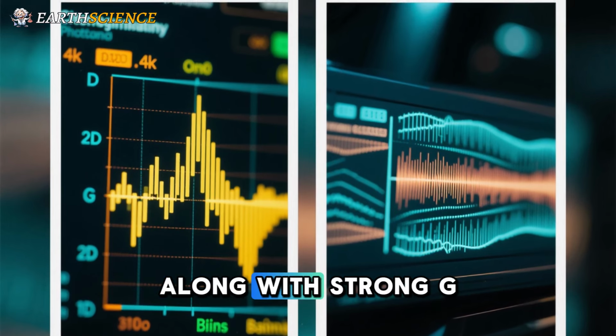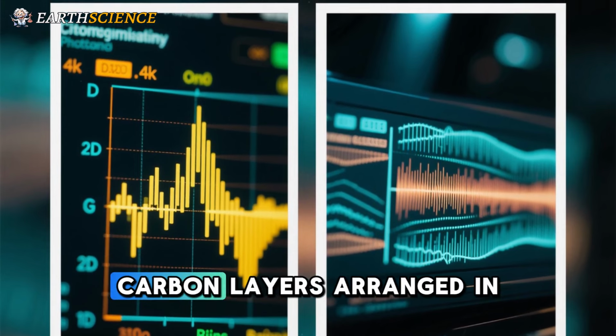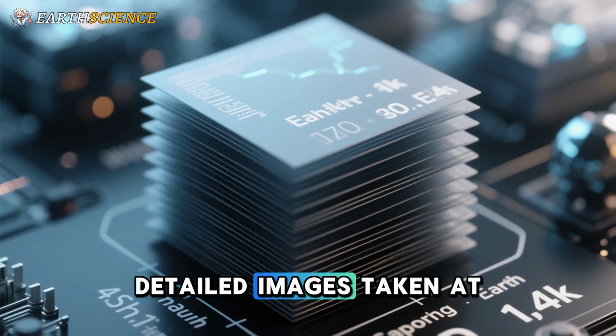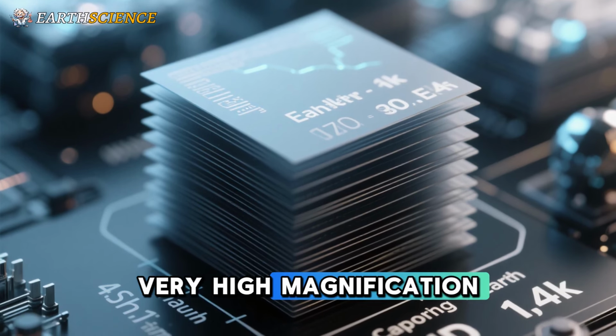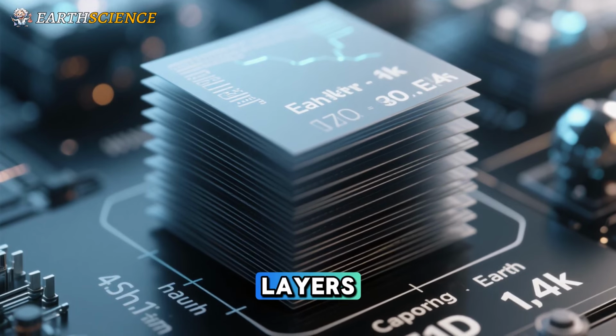The laser analysis revealed a faint D band, along with strong G and 2D bands, a pattern that points to high-quality carbon layers arranged in a graphite-like structure. Detailed images taken at very high magnification confirmed that the material contains stacks of 2 to 7 thin layers, spaced about 0.35 nanometers apart, just like the graphite found on Earth.